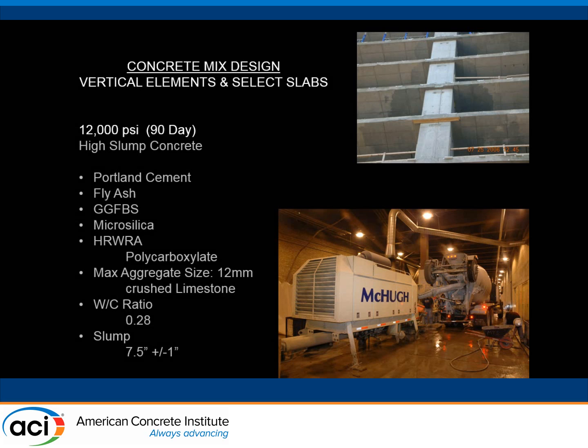But still a generally low water to cement ratio, and here we have a slump of about 7.5 inches, plus or minus 1. I know this has been mentioned a couple times in the session, but you do sort of question what you're getting out of a slump specification. When things were simpler, where you had Portland cement, water, and fine and coarse aggregate, the slump told you a lot about consistency of the mix and what you were getting. But when you have all these admixtures, I think it loses a little bit of its use as a benchmark to gauge the consistency of your concrete.